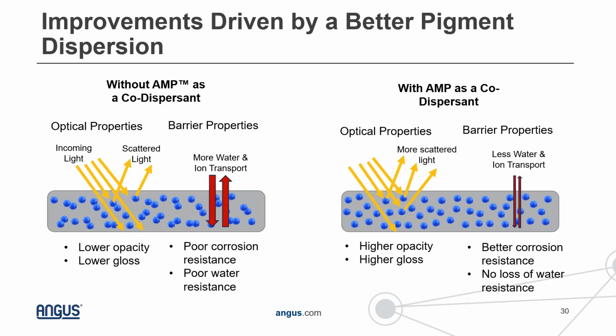So what are the reasons for some of these improvements that we're seeing? Really, a lot of this comes down to getting a better quality pigment dispersion. So in the case of our control formulation, where we're not using AMP as a co-dispersant, if you have a poor quality dispersion of your particles, a lot of that incoming light is not going to have as many opportunities as it could to be scattered. And so you're going to get lower opacity. This can also reduce your gloss. Also, if you have a lot of pigment-pigment interactions, those interfaces can be very sensitive to water. And so you can get more water uptake and also more ion transport, which leads to worse corrosion resistance.